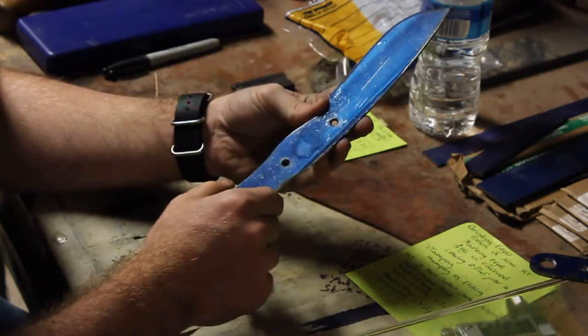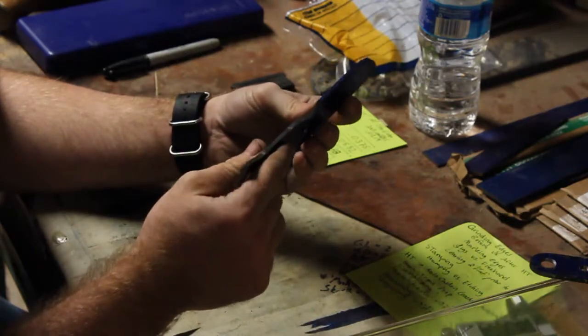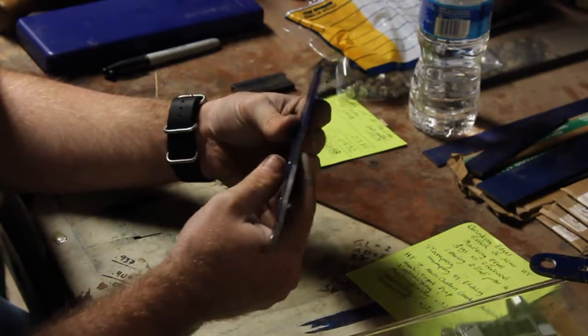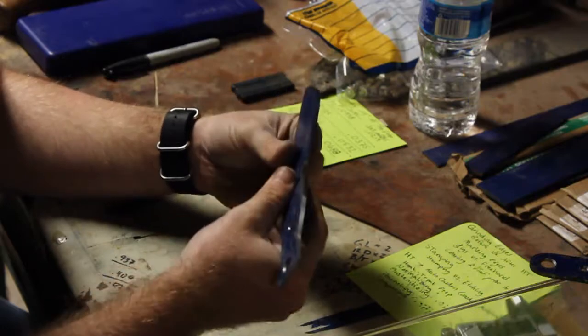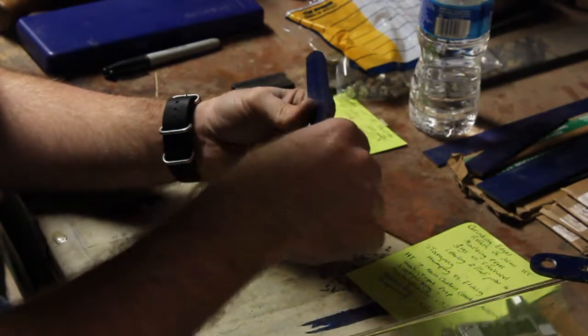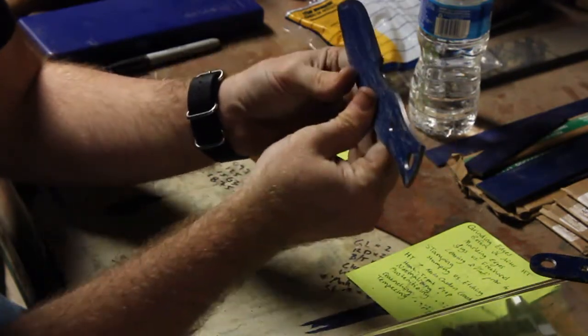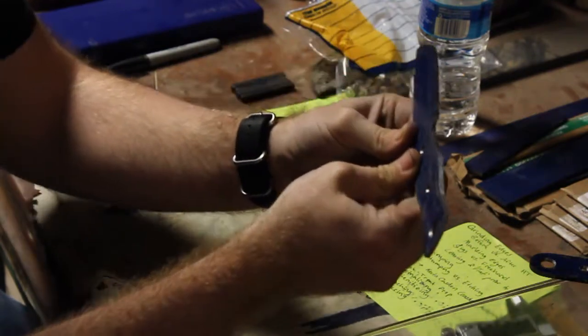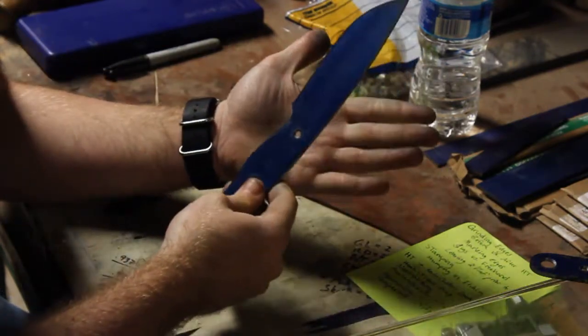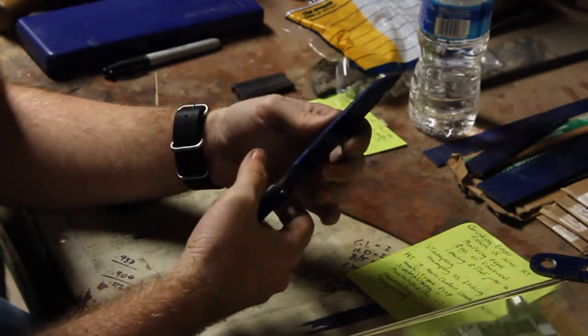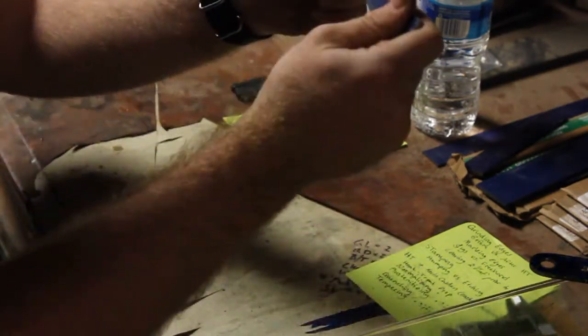Now when I grind Scandi edges, I use a couple of pieces of angle iron where it's clamped and it's flat and it sits upright, and then I move it by hand. Now convex, flat, anything else that I do is all done freehand.